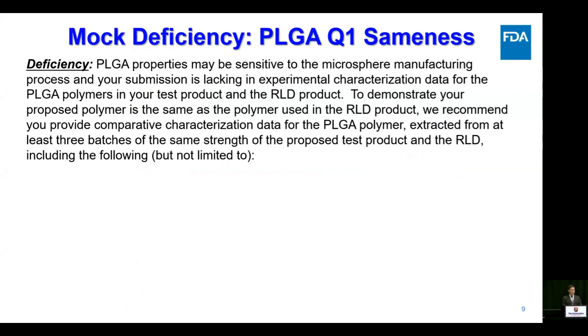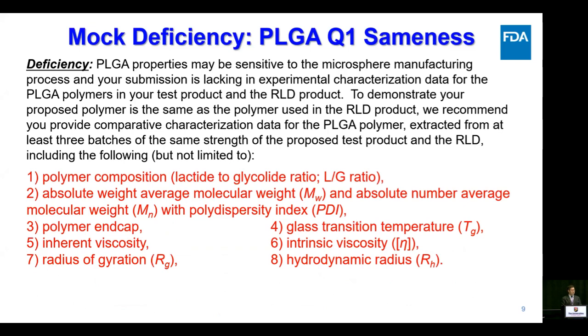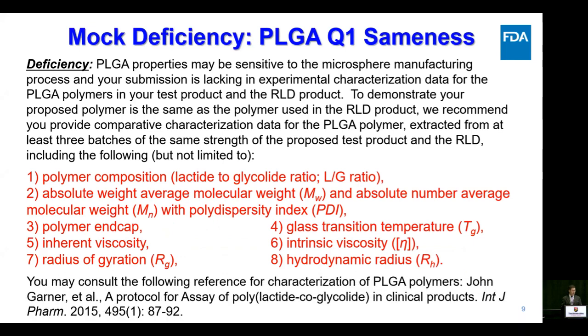characterization data for the PLGA polymer extracted from at least 3 batches of the same strength of the proposed test product and RLD, including the following tests: polymer composition, which is lactide to glycolide ratio, and molecular weight with polydispersity index, polymer end cap information, glass transition temperature, inherent viscosity, intrinsic viscosity, radius of gyration, hydrodynamic radius. For the detail, you can get this publication at the bottom.